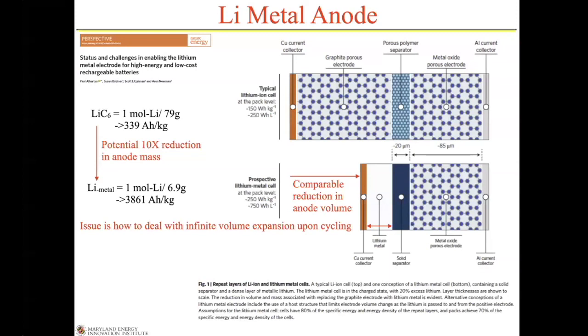How do you address that? If you go to a flat lithium foil for your anode and it cycles, and if you really do 100% depth of discharge on your lithium, you remove 100%. So the volume goes to zero of lithium, and then it goes to 100% on every cycle. That's an infinite volume change every time.